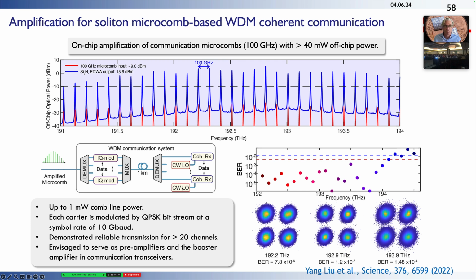So what could you do with these devices? One is you can amplify channels for telecommunications. Shown in red are channels generated by an optical frequency comb at a level of minus 30 dBm, so it's not suitable for transmission. But if you run it through one of these erbium doped waveguide amplifiers, you can comfortably generate power levels of several milliwatts, which is sufficient for coherent communication experiments. So these are very compact amplifiers that could find their way into next generation pluggable optics for interconnects. This is also something we explored with Nokia Bell Labs.